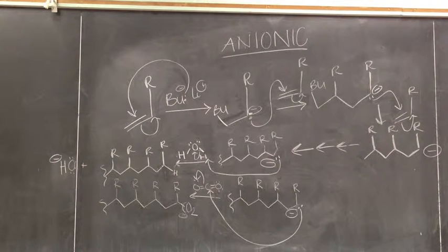But even after all the monomers have been exhausted, the process is not actually terminated until a suitable acid, such as water, or electrophile such as CO2 is added to the reaction mixture. In the absence of a suitable acid or electrophile, the end of each polymer chain will possess a stabilized carbanion site, and the polymerization process can continue if more monomers are added to the reaction mixture. For this reason, polymers generated through this process are often called living polymers.